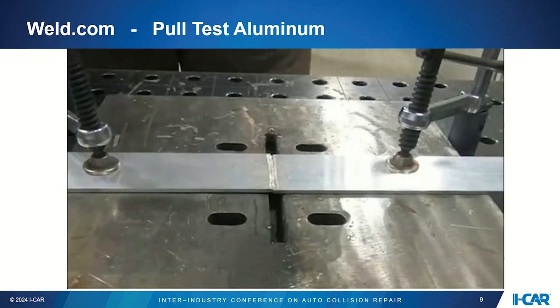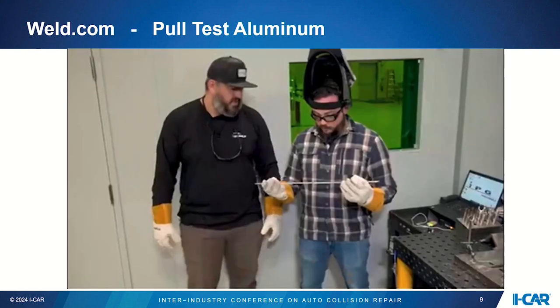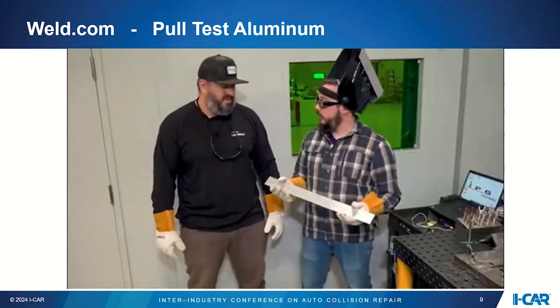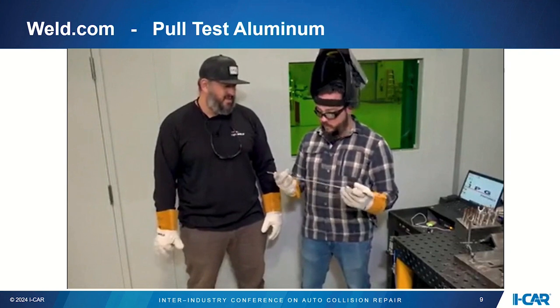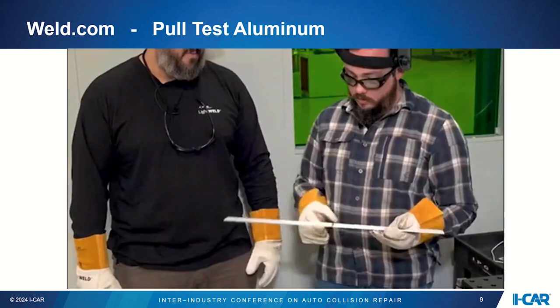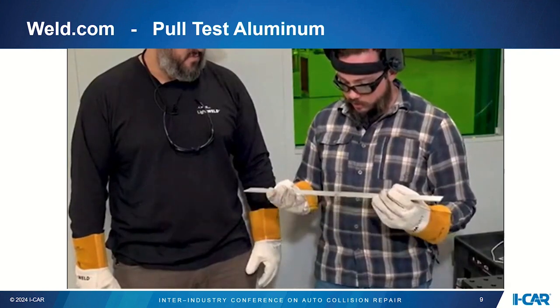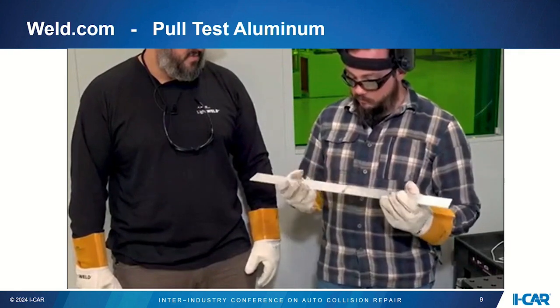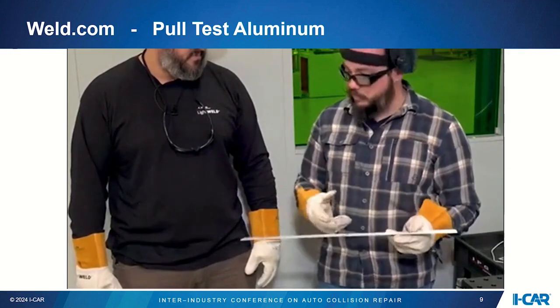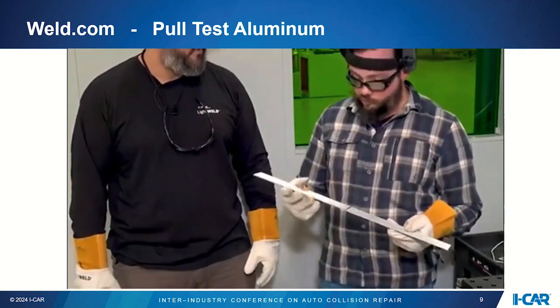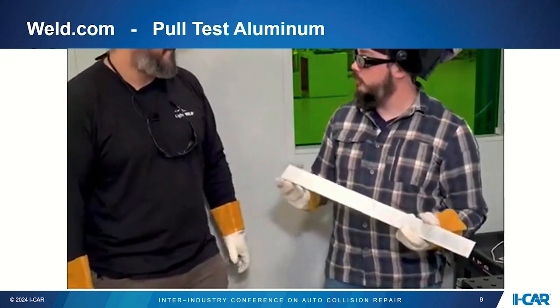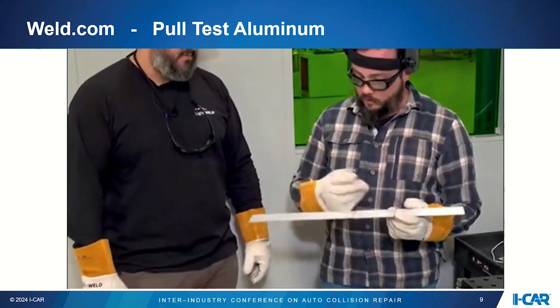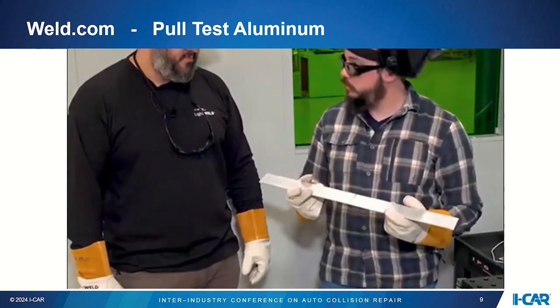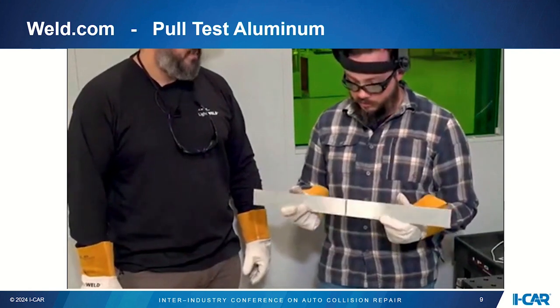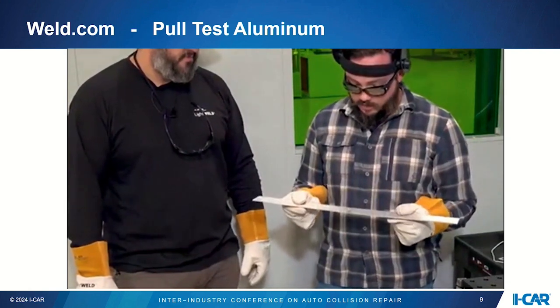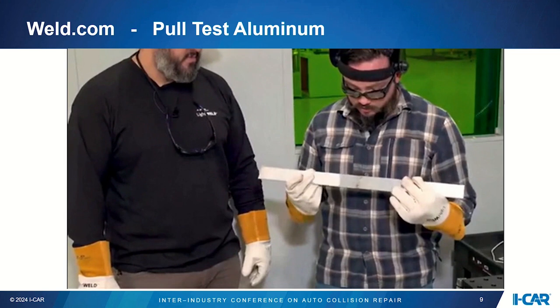So the laser itself, it's a spectrum of light that we can't see. That's right. It's infrared. So it's 1090 nanometer. It's just outside of the visual. Okay, so any light that we're seeing there is UV light. It's about 1/10 of the UV light as MIG or TIG. You're not going to get a sunburn at laser welding, that's for sure. But the white light you see is UV. It's not doing any work. It's just a byproduct of the weld itself.